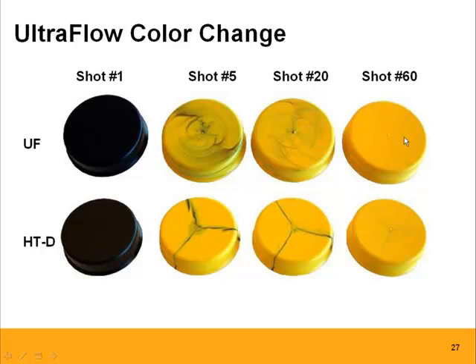With a standard tip, because we're concentrating the color by splitting the melt in these 3 areas, it's a lot harder to disappear, and you can see after shot 60 there's still a slight trace of that colorant in the part. And that's why the UltraFlow tip speeds up color change. I would also like to point out one of the other things the mixing function of the UltraFlow tip does: it homogenizes the melt right before it enters into the cavity, and in some cases that has proven to enhance the mechanical properties. More homogeneous melt, less flow lines, better mechanical properties of the plastic part.